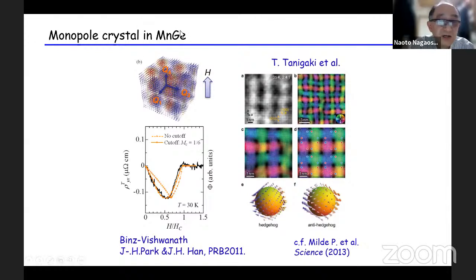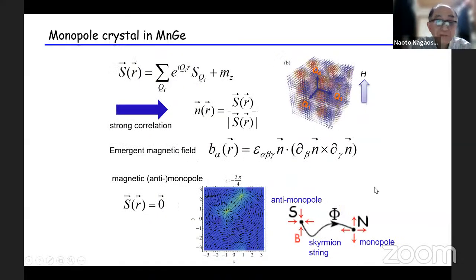So these materials I just mentioned show an even more interesting magnetic structure, a so-called monopole crystal in the low magnetic field regions. So this is again the Lorentz microscopy. And from this, they propose that the magnetic structure contains a hedgehog and anti-hedgehog. So in the language of this Berry curvature, this structure corresponds to the monopole and the anti-monopole of flux. Namely, you can calculate the B field along this monopole and anti-monopole. So you have a source and a drain.